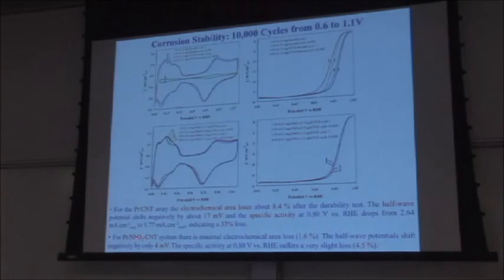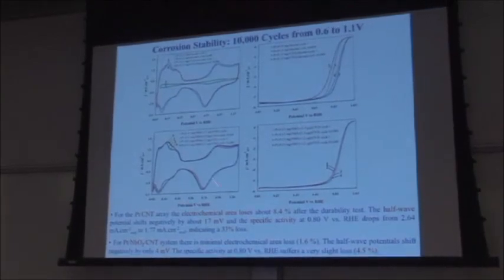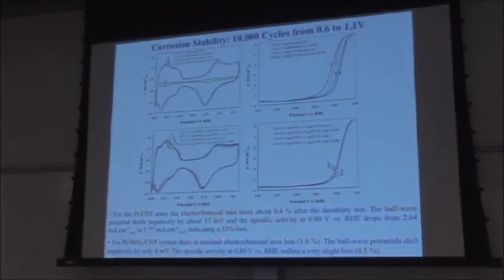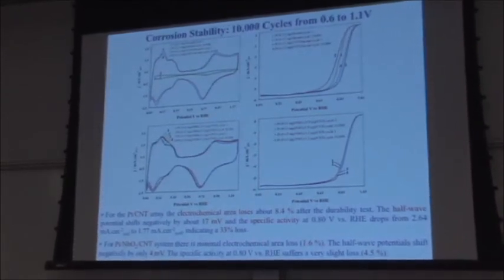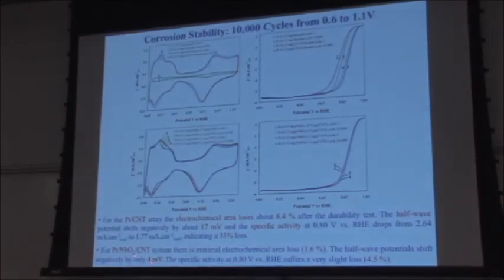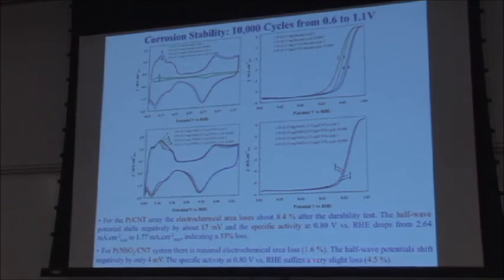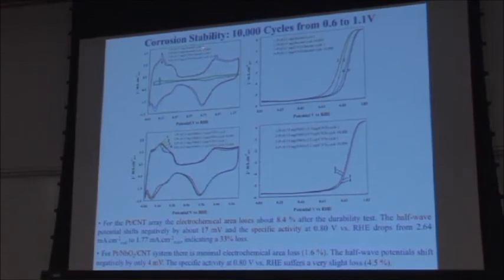If you introduce a thin niobium oxide layer, you essentially have a negligible decrease in the activity. So your electrochemical area loss is 1.6% versus 8.4%. Half-wave potential shifts by 4 millivolts, and specific activity shifts 4.5% versus 33%. So these are the CV curves. Never mind the green one, that's just the planar baseline. The change in area tells you how much platinum you dissolve, to first approximation. But you see the shift in the overpotential for the platinum on carbon nanotubes and platinum on carbon nanotubes with niobium oxide.